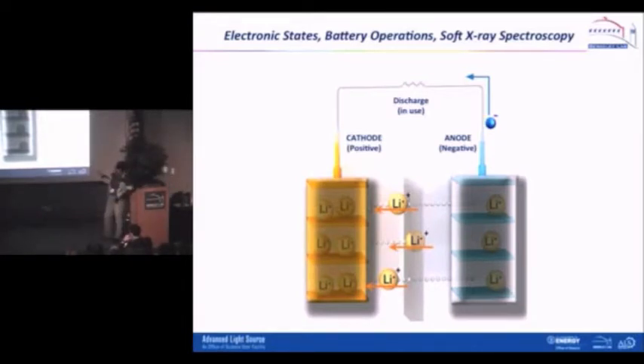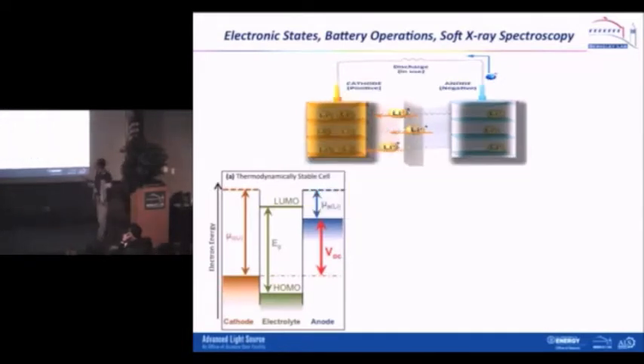So when you drive the electron or lithium from the anode to the cathode, the energy gain you get is actually the chemical potential between this anode and the cathode. This chemical potential difference gives you the so-called open-circuit voltage. The voltage is very important in a battery because it determines the power of your battery. In other words, if you use this battery in your electric vehicle, it determines how fast you can speed up your car so you can merge into the freeway safely. So this voltage is determined by the chemical potential of the anode and the cathode.